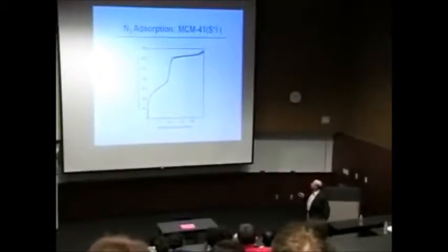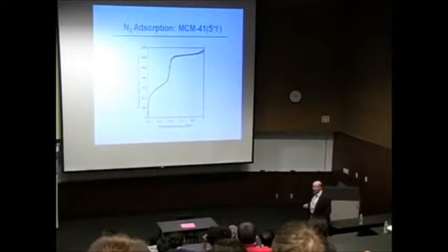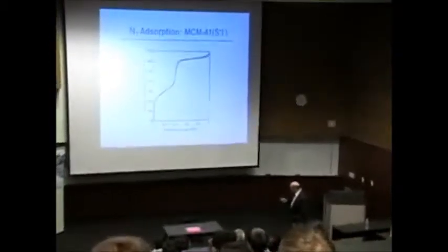In other words, as the pore size increases, you need to put in more driving force to force liquid formation in the pores. So diagnostically, just by looking at the adsorption isotherm, you immediately could get an idea of the relative pore size depending on where the step is located, and how well ordered the pores are based on the vertical shape of that step. Okay? That's a very important thing to keep in mind.